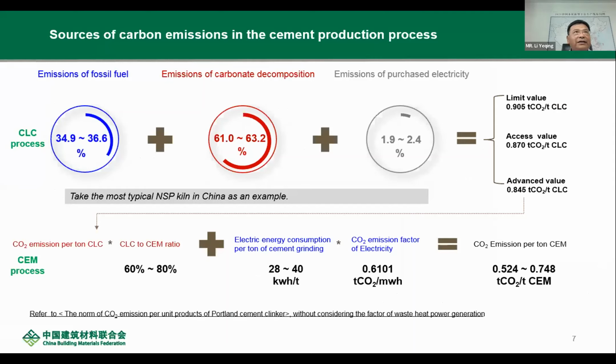Let's look at this data of carbon emissions in the world cement production process. We take this NSP kiln as an example, which is the typical and advanced pre-calciner kiln system in China. From this system, we can see the carbon emissions per ton clinker is around 860 kilograms per ton clinker, or 850, which is better practice.